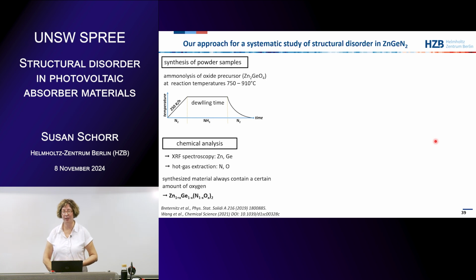Now we have to synthesize the material, and it was not so easy to synthesize zinc germanium nitride. We started with an oxide precursor, zinc germanium oxide, and then we did the ammonolysis reaction. So we reacted this with ammonia in a closed tube at a certain temperature and for a certain time. Then we did the chemical analysis by XRF spectroscopy to get the zinc and germanium values. And then we used something which we could do at the Technical University Berlin in the chemistry department. We did what they call hot gas extraction, and then we could determine nitrogen and oxygen content.